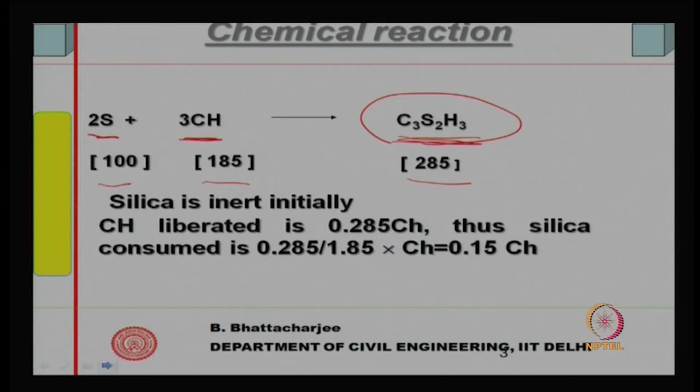If you directly mix with lime, then the reaction can follow with lime itself. But if you recall the lime reactivity test, we use lime together with silica, and the demolding time was about 48 hours, which means the reaction does not occur very rapidly.